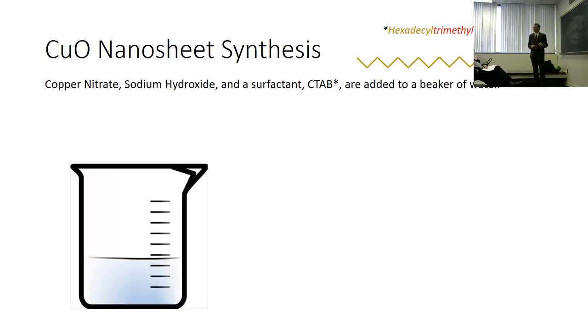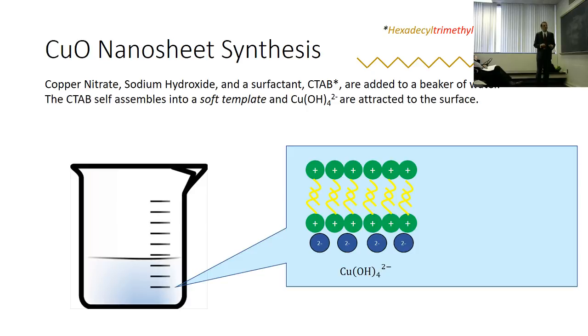It acts as a scaffold or a soft template for the synthesis. When you put a surfactant in solution, the hydrophobic parts, in a water solution, hide because they don't like interacting with water, and so the hydrophilic part points outward. What's going to happen is we try to attract the copper to the surface of this surfactant scaffold. But you might have noticed that this is a positively charged surfactant. Why would you use a positively charged surfactant to attract copper, which has a +2 oxidation state?